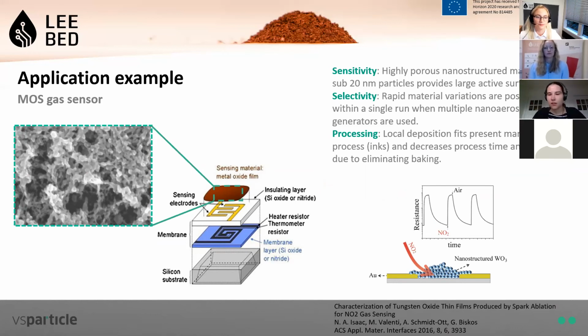So how does such a sensor work? You see the little schematic in the right bottom corner. In the presence of an analyte gas, the resistance of the metal oxide changes as the target gas adheres to the surface of the metal oxide. And then there it reacts with the oxygen that was previously attached. And so if you change from your analyte gas to air or oxygen, you can change the resistance from high to low.